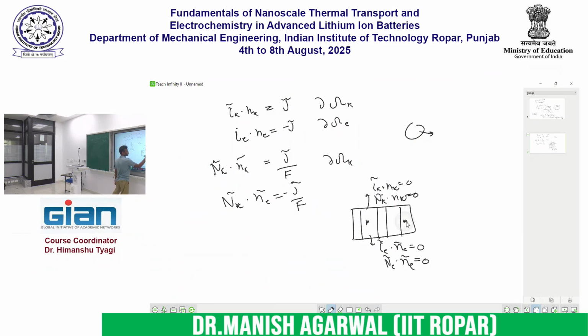What will be the phi value here? Whatever you are prescribing. Especially, it will be phi equal to 4.2 volt if it is a potential driven problem. If it is a current driven problem, then rather than prescribing the potential, you will prescribe the current.